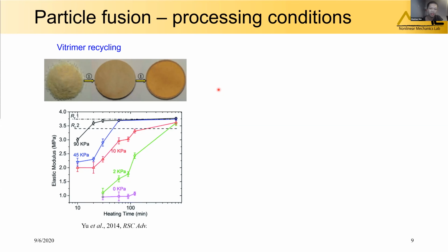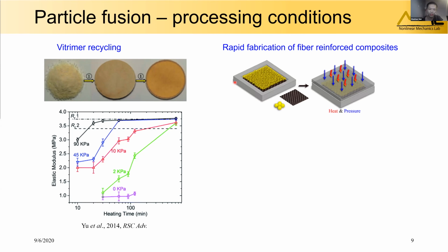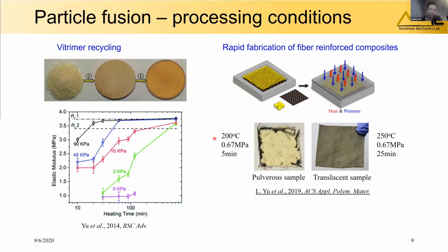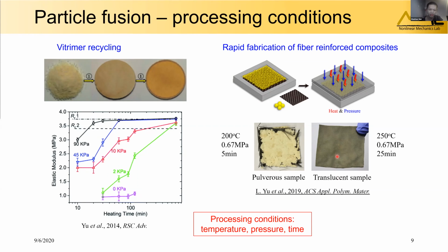So this is motivated by two questions. In the application of the Vitrimer recycling, the different pressures as shown by different lines and the different heating times can lead to the material with different elastic modulus. And in our recent work, we have demonstrated the rapid fabrication of the fiber reinforced Vitrimer composites based on heat pressing the polymer powder and the carbon fiber mat. We also see that the temperature, the pressure, and the heating and the processing time can significantly affect the fusion quality of the Vitrimer matrix. So how the processing condition affects the fusion process is the first question.